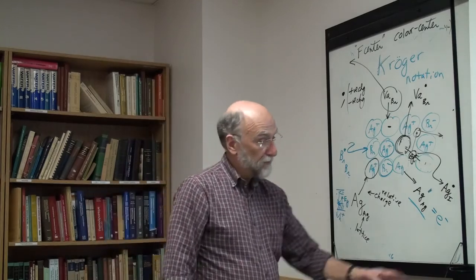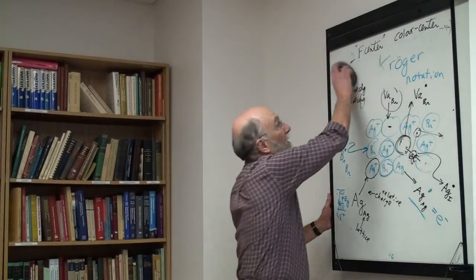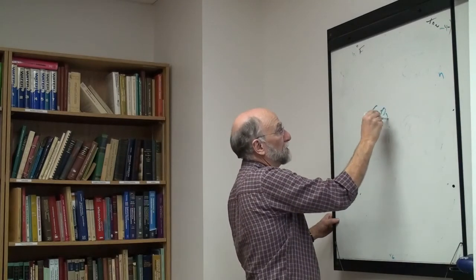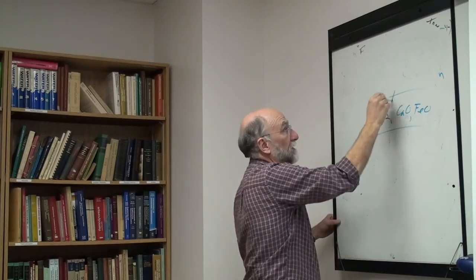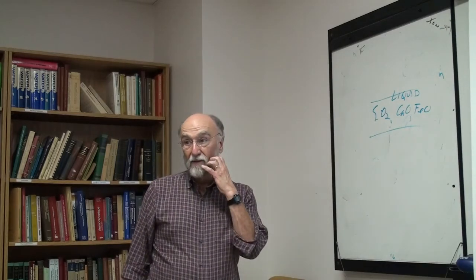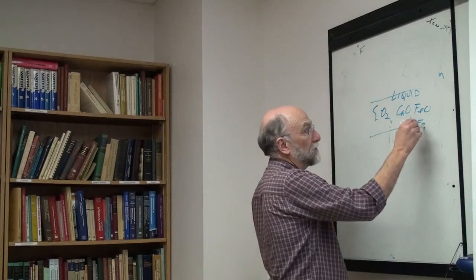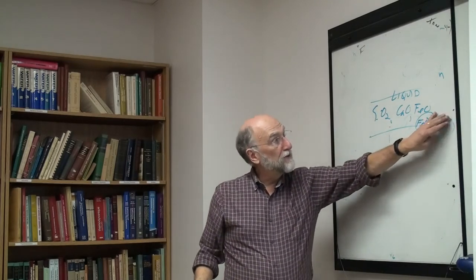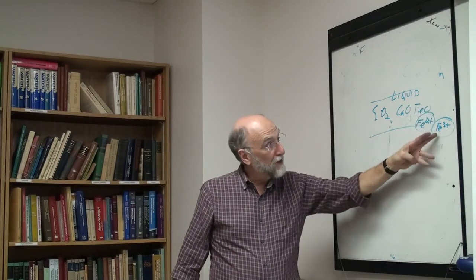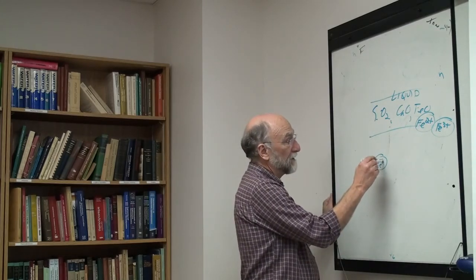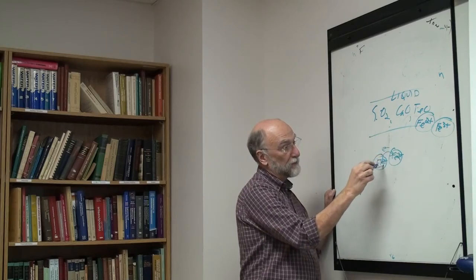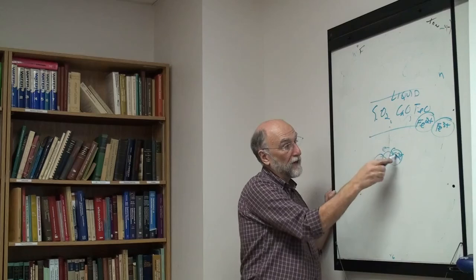However, this whole conduction thing, of course, is important, the electronic conduction, because you do get hopping. If you take a slag, SiO2, CaO, FeO, whatever, liquid slag, the liquid slag is normally an ionic conductor. There's no electronic conduction in it. But if you have Fe2+ and Fe3+, if you have only Fe2+ or only Fe3+, then it's only an ionic conductor. But if you have some of both, then electrons can hop, because here you have an iron ion, Fe2+, and next to it you have an Fe3+. An electron can hop like this. This becomes a 2+, this becomes a 3+. The ions don't have to move. They stay there, the electron just hops.